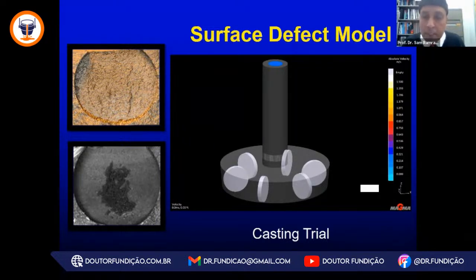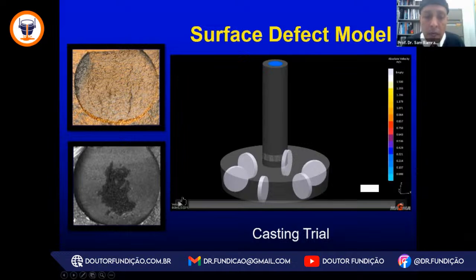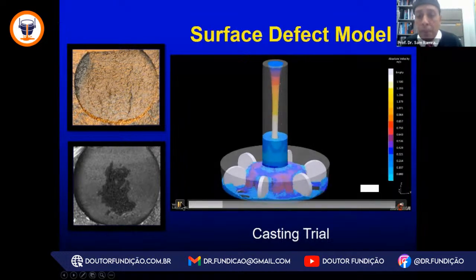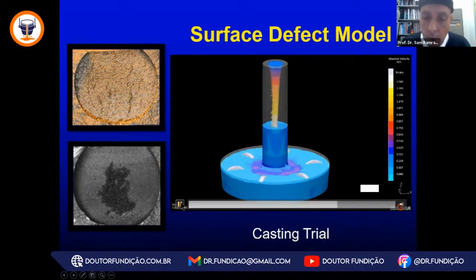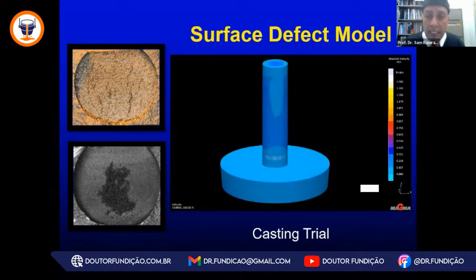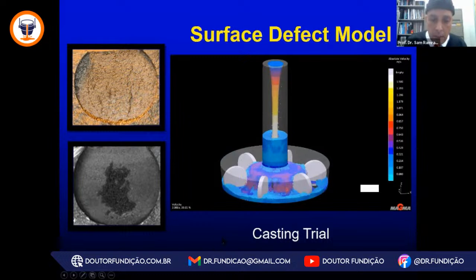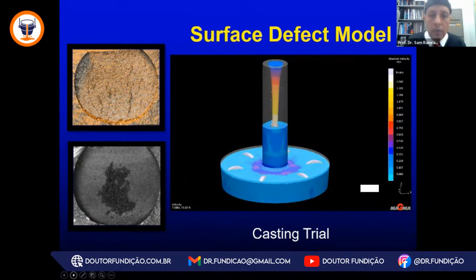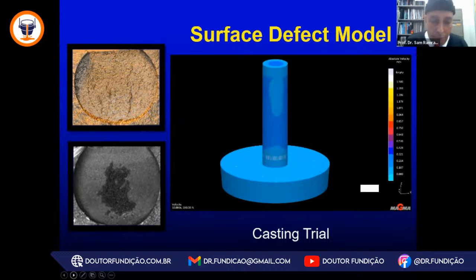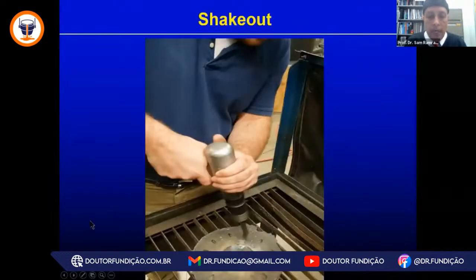And we place these different recipes under the same head pressure, under the same metal chemistry, and the same superheat. And we wet them in that relationship. When this particular casting has solidified, we can shake out these castings. Okay, let me show that again. We fill it, and then we perform the qualification against the chemistry, the superheat, and the head pressure.